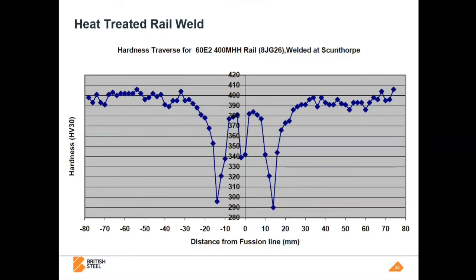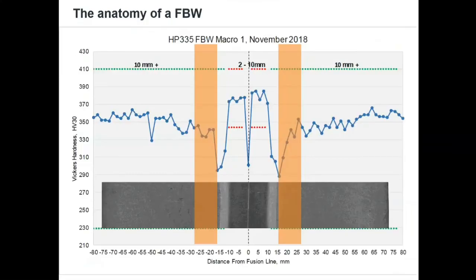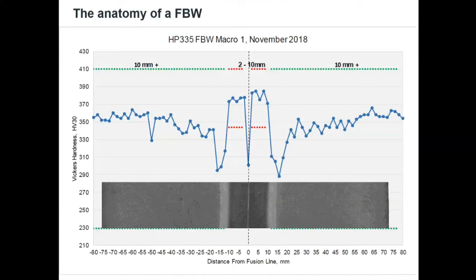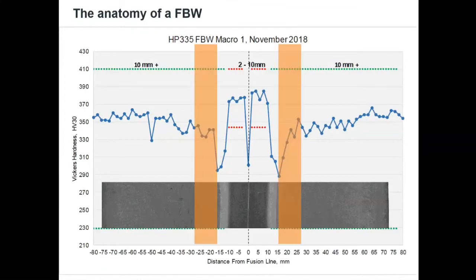And that's where the heat treated rails let themselves down a little bit. The critical heat affected zone is always slightly weaker than the parent, and they become the dominant factor in deciding your maintenance frequencies. Whereas if you go back to HP, you can see that the critical heat affected zone is always harder than the parent, and therefore it's never the factor that lets the rail down.